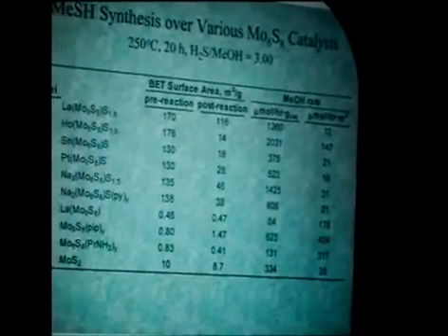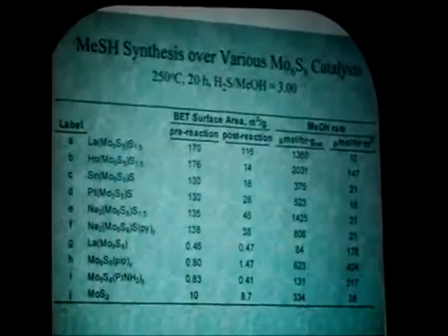Another thing to notice is that the rate of methanol conversion is highest on a per gram basis for the amorphous materials, and higher on a per meter squared basis for the crystalline materials, implying that some of the surface isn't really accessible. We should expect similar results for those numbers if all the surface was the same, especially comparing the lanthanum Chevrel material to the amorphous material.